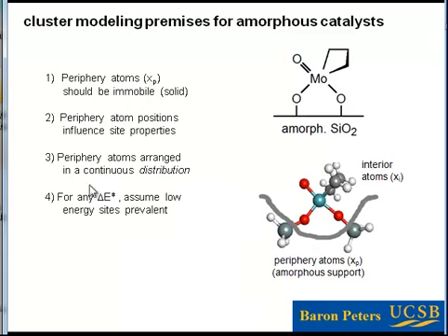Okay, the fourth point to make here is that for any given activation energy on this site, suppose I were to compute the rate on this site and compare all sites that have the same rate. There are of course sites with different rates, but I'm going to look at just the ones that have the same rate. There are probably many ways to get the same rate on a given site, same turnover frequency. And what we expect is that the site that has the lowest energy among all of those sites that have the same turnover frequency is the most common site with that turnover frequency, right?